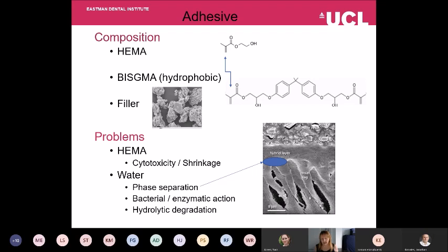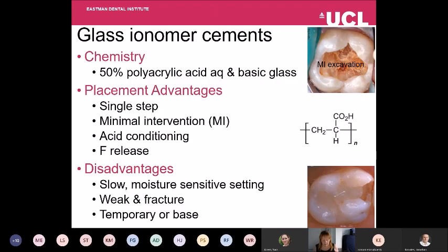The problems, though, with HEMA: it's a small molecule, it's cytotoxic, it has high shrinkage when it polymerizes. You can also have the hydrophilic and the hydrophobic components phase separating from each other when you try and mix them. And you can get pockets of water where you can get continuing bacterial action, continuing enzyme action, causing degradation of remaining collagen and dissolution of apatite. Also, because the HEMA, when it's polymerized, is still very hydrophilic, you can draw in water, and that can cause it to degrade. The alternative for children is the glass ionomer cement.